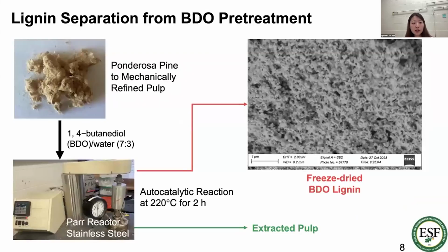First of all, we produce lignin using ponderosa pine and the BDO lignin process. We first mechanically refine the ponderosa pine, and then using a butanediol and water mixture, we react it in a Parr reactor at 220 degrees Celsius for 2 hours and extract the lignin. We used the BDO extracted lignin, washed and freeze-dried, as in this figure on the slide.